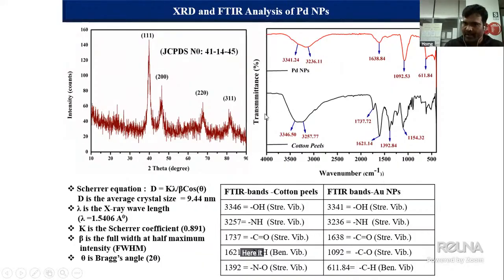Here only the extract is identified by FTIR, and here we identify the palladium nanomaterial. We can say these are polyphenols, that means biomolecules. The biomolecules reduce and cap the nanoparticle. A capped nanomaterial is superior for catalytic activity. While it is a functional material, the material is covered with the biomolecule. That ultimately enhances the potential for catalytic activity.